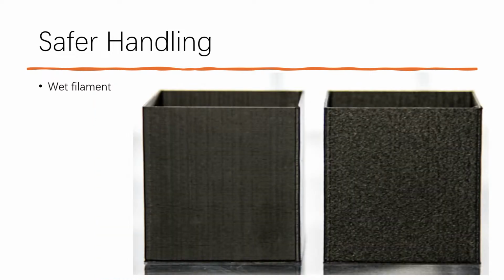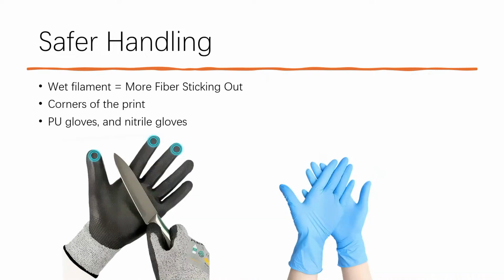And also, this is another case where you have to be careful. If your filament is wet and has moisture in it during printing, the moisture is going to vaporize. It's going to push things around. So with wet filaments, there's more chance to push the fiber off alignment, so there's a better chance the fibers stick out a little bit more. So that's another reason for you to keep your filament dry, because otherwise your fibers are going to be sticking out on the side.